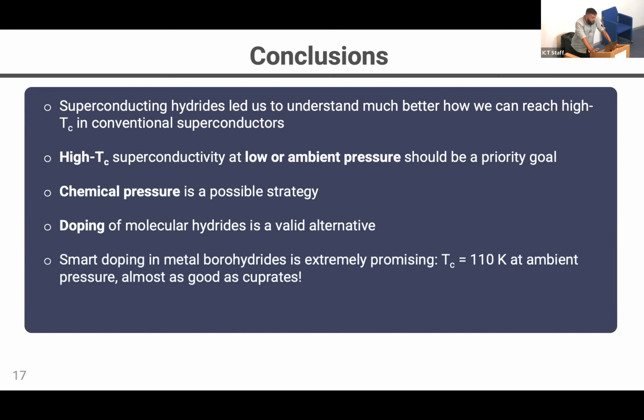So I hope I convinced you that smart doping in metal boron hydrides is extremely promising, and that we predicted a TC of 110 Kelvin at ambient pressure, which, if this was realized, would be almost as good as cuprates. And that we also have alternative doping routes in boron-carbon systems.